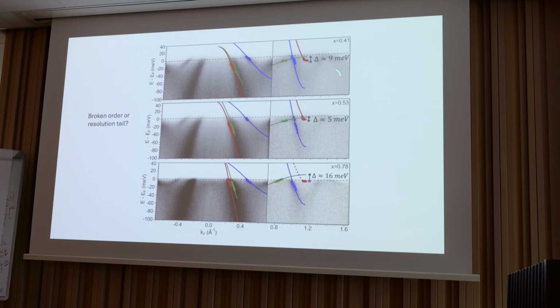We're not claiming that there's any broken order here, but maybe this gap between the band top and band bottom is within some error bar. But it's bigger for 78%. So this is still an unresolved question for us, of whether this is some broken order or just some trivial thing. But I think it is interesting that this occurs in the vicinity of so many other instabilities that we've seen and that have been talked about. So something to keep in mind. But then again, this gap opening here is this three-band model that Vadim and Igor have been talking about that might fit this broken time reversal symmetry picture.